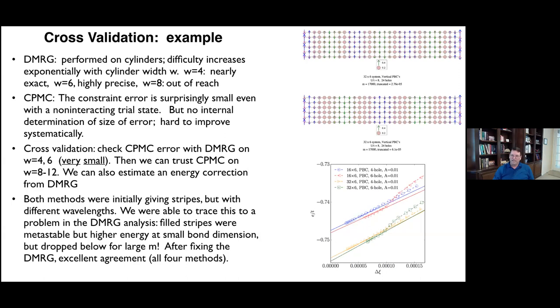And so we did not look at this carefully enough until we were looking at the quantum Monte Carlo and trying to resolve the differences. And then once we looked at this, it agreed very well with the Monte Carlo. So that's an important potential mistake to look out for when you're doing certainly DMRG, maybe other sorts of methods also.